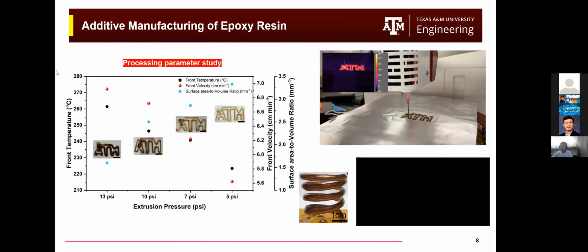And then by tuning the processing parameters, such as the extrusion pressure of the printing process, we can also significantly lower the frontal temperature, and the frontal velocity is also reduced as a companion with the frontal curing temperature. So here, we also compared how the frontal temperature affects the performance of the material. Here we found that the tensile strength significantly increased as the frontal temperature is reduced, which is desirable for the printing process as well as the part performance.